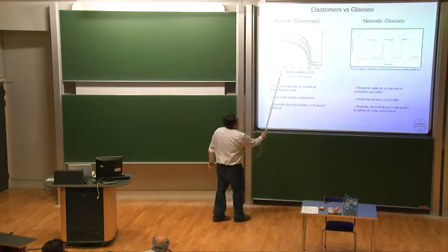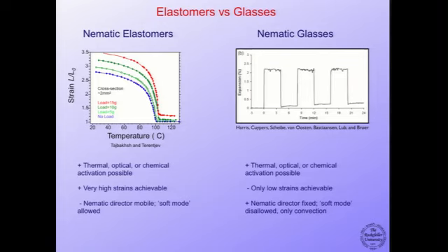This is you cycling the order parameter. So you're looking at how much, for some given load, you give it a set weight on the thing, and at some temperature it has some certain length extent, and then you change the order parameter by changing the temperature, and the material elongates. If you're cooling, it pulls up; it contracts the other way. It's not a stress-strain curve. It's a temperature response. You're flexing the weight with temperature.